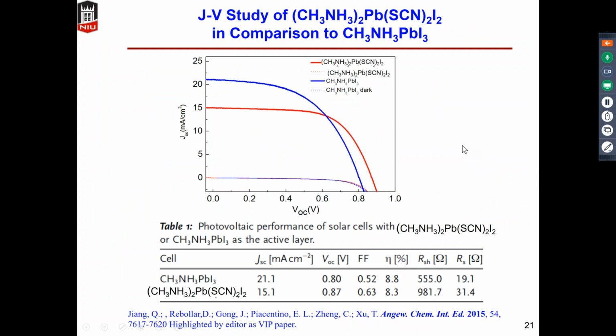However, when we measured the efficiency, it seems that this pseudo-halide-based perovskite is not very competitive with the conventional MAPbI3-based perovskite solar cells. And this work was done in our lab. At that time, our lab had the capability of making conventional MAPbI3-based perovskite at an efficiency of about 12%.